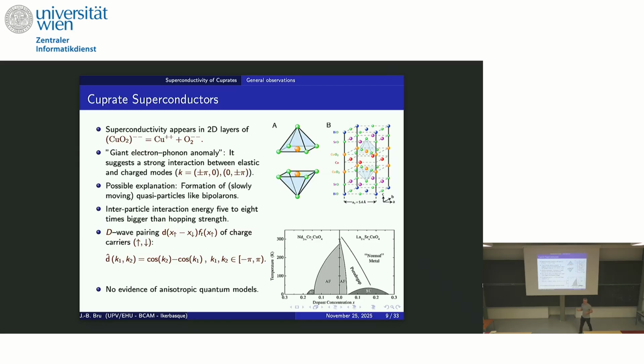So what they did, as you do for semiconducting material, they dope it. For example, in this case, they add this atom here, strontium, I think its name. And by doping it, at the beginning you have a Mott insulator. That means that on each lattice site, for example on your two-dimensional layer, you have typically an integer number of electrons. So adding a little bit of doping, you add extra holes or extra electrons, depending on the doping, and this breaks the Mott phase.